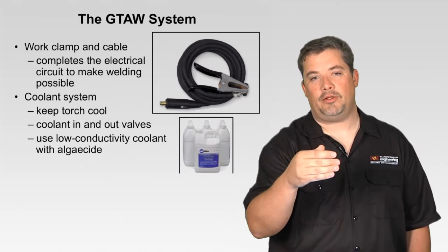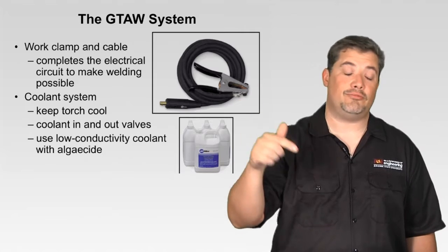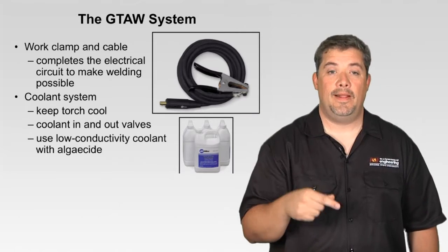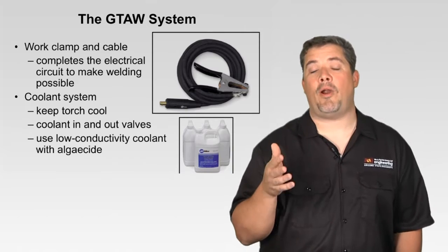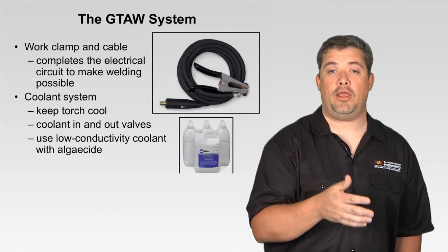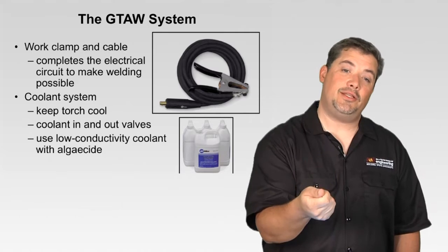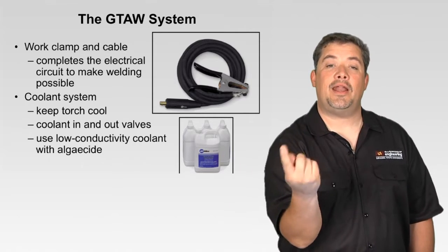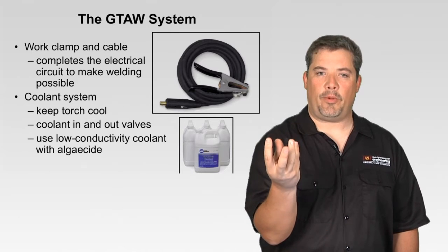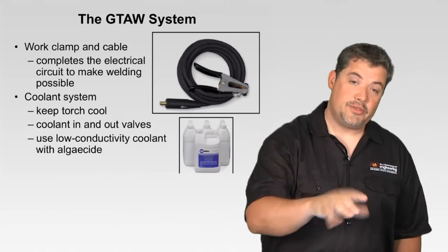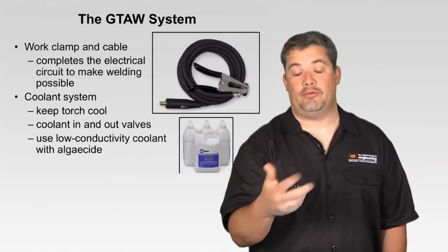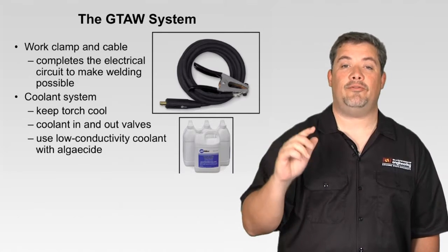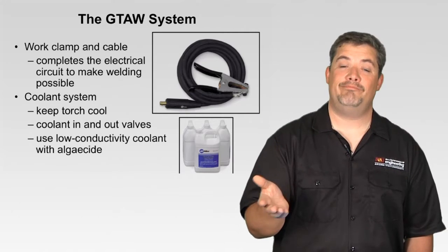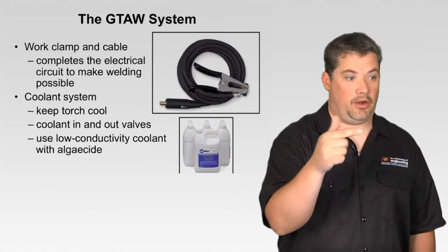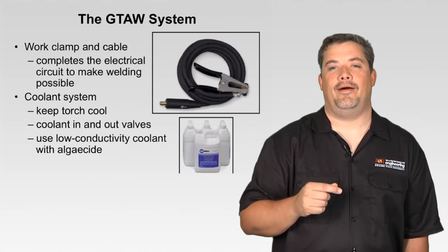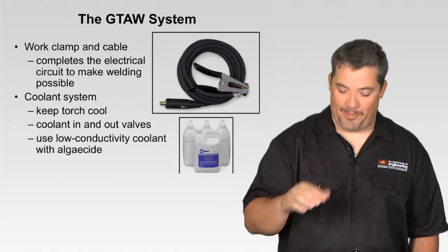Another story real quick too, an environmental story. Companies will have in the past literally just run tap water through their torches and put it down the drain. I had a company here in Phoenix, that's what they were doing. They were getting a lot of porosity in their aluminum welds. And it happened mostly in the morning and mostly after lunch. Why? Because that torch was just sitting in the shop, cold water was flowing through it, and so they were getting condensation up in the side of the torch head on the copper parts that were being cooled, and so when they would be welding, they'd be introducing hydrogen into their weld. Well, hydrogen equals porosity in aluminum, and it equals suicide in your weld. So once they bought coolant systems, put the right stuff in it, all those quality issues went away, and being in Arizona, it's probably a little more environmentally friendly to make sure they weren't just dumping that water down the drain. I actually gave them a hard time on that as well to help influence their decision to buy coolers. But anyway, side story.